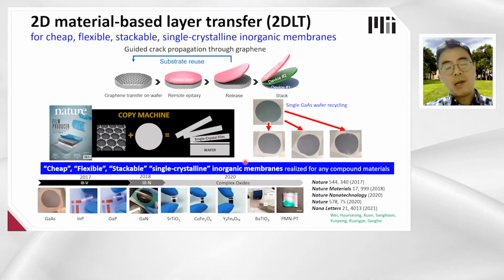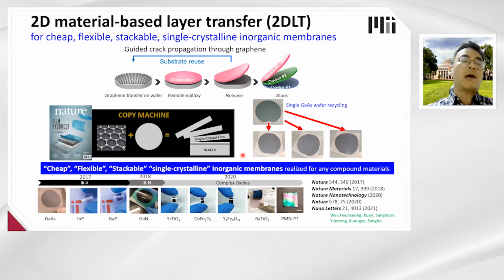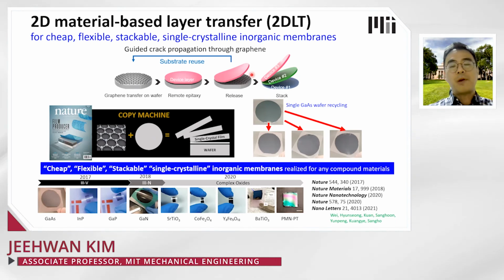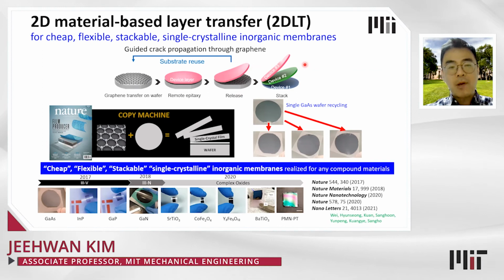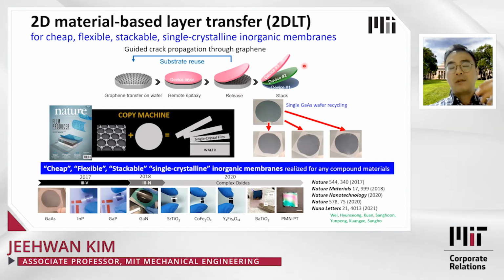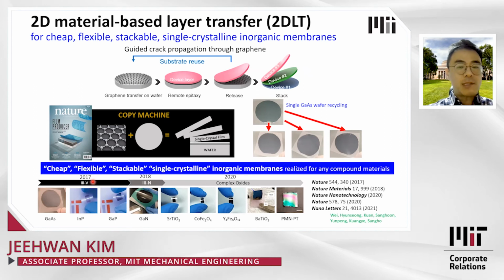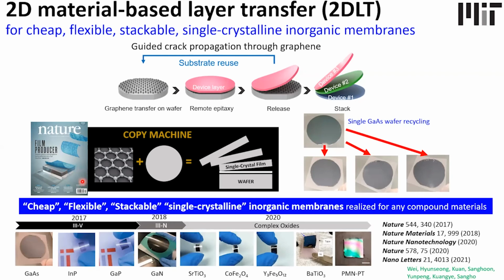By having this capability, by growing perfect single crystalline material on graphene, by peeling off entire films from the substrate, and by stacking them up, we can really revolutionize future electronics. Ever since 2017, right after we published this technique in Nature in 2017, we have expanded the material systems that can be made in the form of freestanding materials. In 2017 we were able to do it for III-V materials, in 2018 for all possible III-nitride materials, and in 2020 for all complex functional oxides.